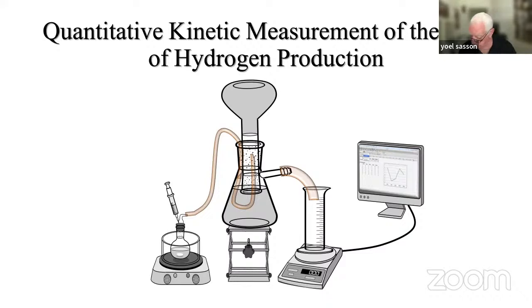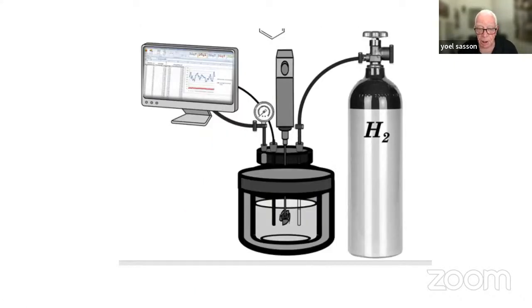This is a very simple and easy to follow methodology for quantitative kinetic measurement, and you can see our reaction taking place here. You inject the formate solution, then you have this trap to measure the volume of hydrogen being released, and simply wait to calculate the rate of the process. This is for hydrogen release, and this is for hydrogen charge under pressure - again following the pressure change with time so you can follow the kinetics.